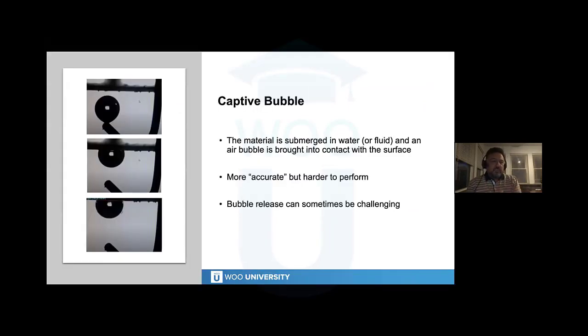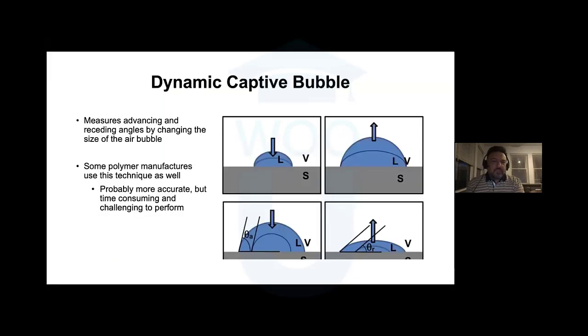So another method which is a bit more accurate and not as vulnerable to wettability issue or evaporative issues is the captive bubble method. And this is a situation where you have a lens material which is actually submerged in water or another fluid, and instead of dripping liquid down onto it in air, you release air up from below it, and the air bubble rises to the surface of the material, and then it spreads out as well, where the surface material and the fluid that it's in will cause the resisting of the bubble to spread. Again, this is a more accurate but harder to perform method, and has its shortcomings, and the bubble release can sometimes be difficult.